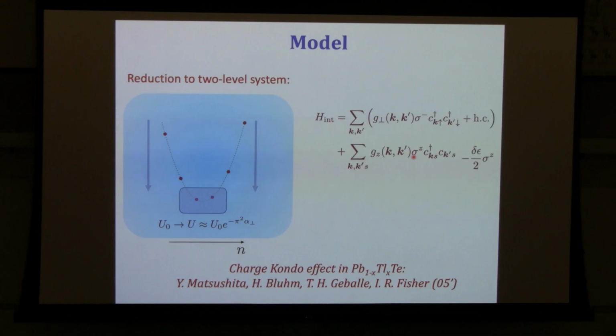So this is a model of a two-level system interacting with electrons. In other words, this is actually a very familiar problem in condensed matter physics. This looks almost like the so-called Kondo problem of an actual localized spin interacting with a metal. But the difference is that it's not a spin, it's a pseudo-spin. The two levels are not up and down, they're n and n+1 Cooper pairs. And it turns out that that can also create a Kondo effect. There's something called the charge Kondo effect, which is exactly a realization of this type of Hamiltonian. It's a very different system, but it's been discovered here by Ian some years ago. So this is actually the problem that we'll study.